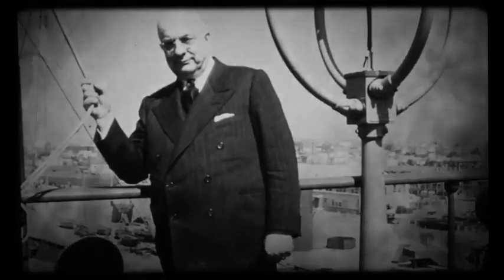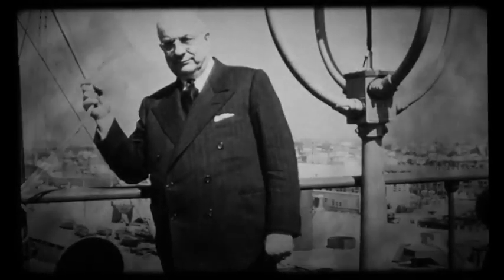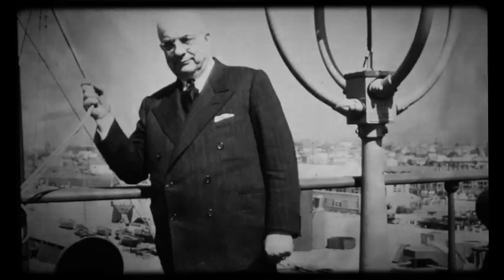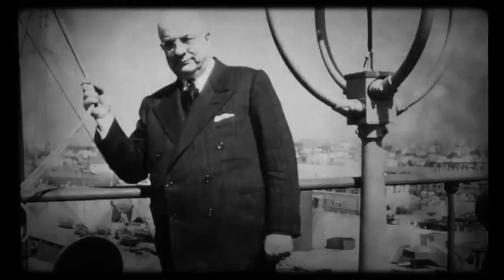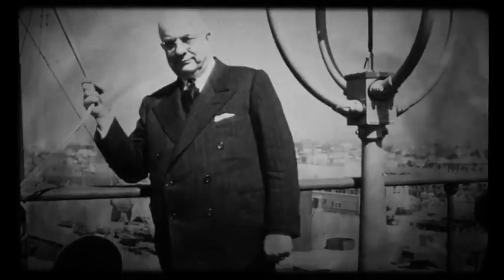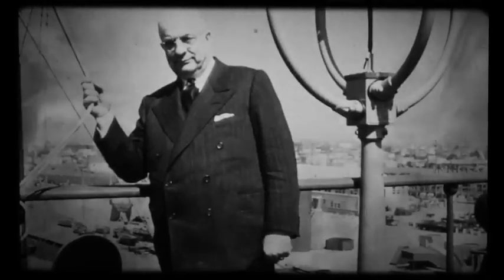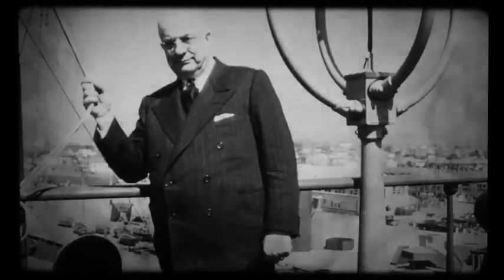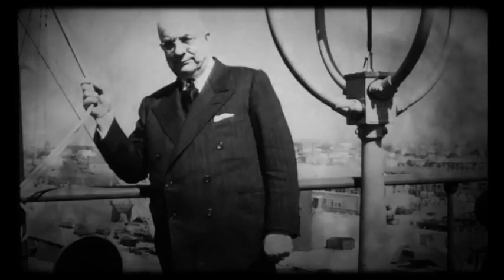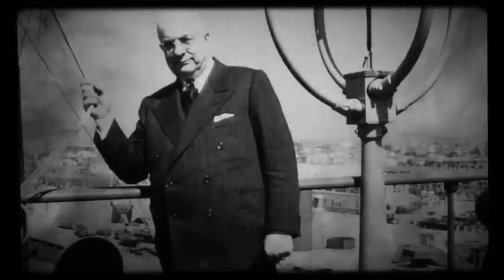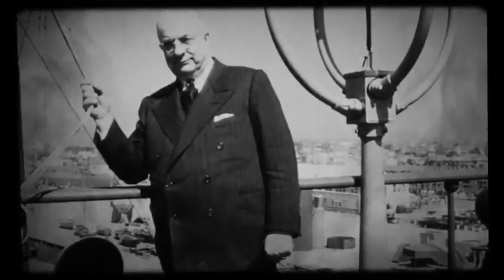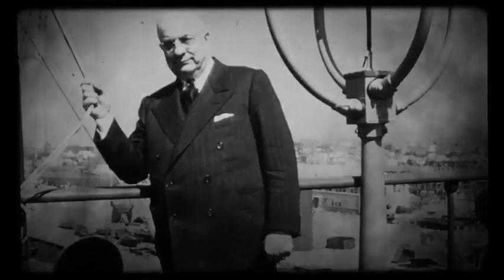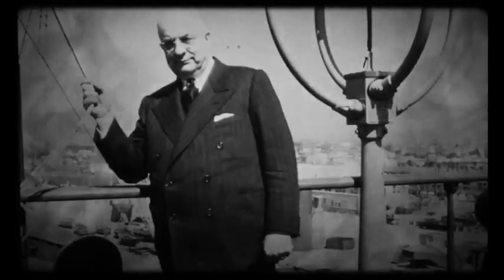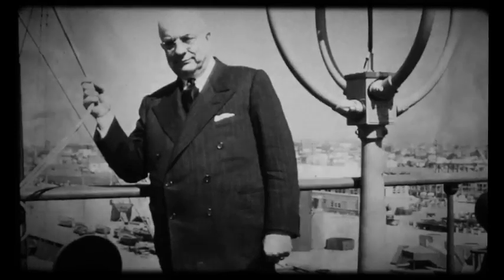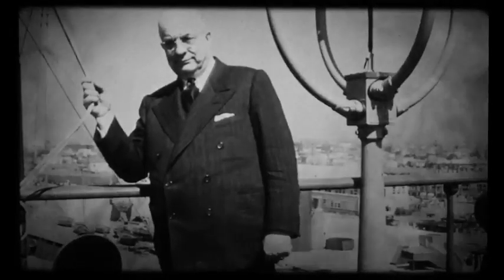At first, about 15% of welds failed the test on the first Victory ships, but workers learned fast. By the middle of 1944, the failure rate dropped below 3%, which showed how well the training and the new rules worked. The proof came when the ships went to war. Between June 1944 and the end of the war in August 1945, 531 Victory ships were launched, and not one broke apart or failed completely.